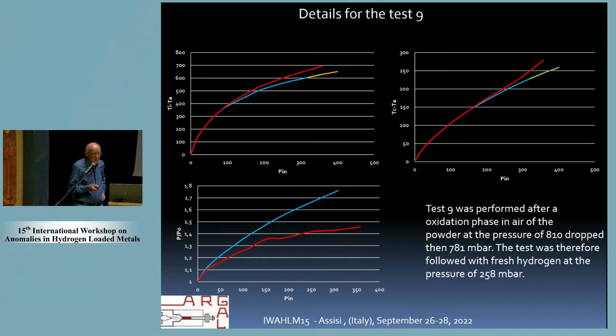Making a treatment to the powder, an oxidation to regenerate the behavior of the powder, we had with the next test very good results again, having a quite high response in terms of extra heat. Here we have together again the internal temperature behavior and the chamber temperature, in comparison with the calibration, with a small extrapolation because the calibration was not at such a high temperature. Here there is again a quite good behavior about absorption of hydrogen.